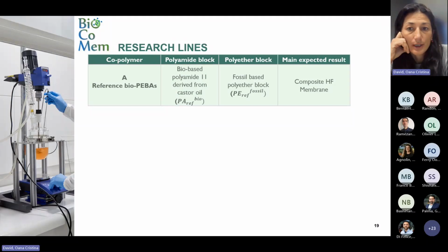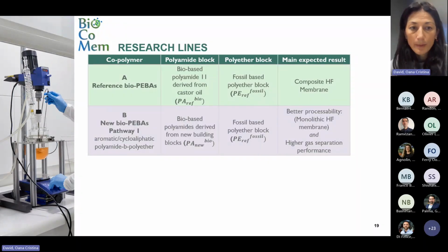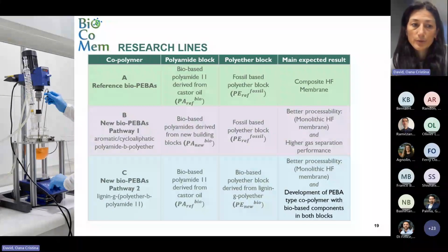So we had the first research line trying to make composite membranes. And these are the flat sheet membranes that Herion showed before. And then we wanted to change the polyamide chemistry to be able to make PEBA monolithic hollow fiber membranes. And in this case, for this research line, we kept the polyether oxide chemistry fossil fuel based. We kept it constant. And then finally, we also wanted to try to make a fully bio-based material, with polyether oxide and polyamide parts bio-based. And at the end, we were thinking that we will check if we can make monolithic hollow fiber membranes, or we need to make a coating procedure.